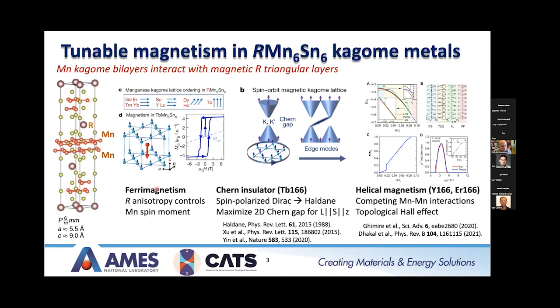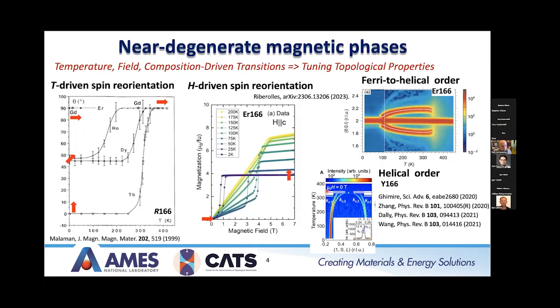So as I said, a lot of these heavy ones, you get ferrimagnetism with the rare earth anisotropy controls. But then also on the other side, if you go to non-magnetic yttrium and even for erbium, as I'll show you, you get competing manganese-manganese interactions, competing interactions between the layers, which can lead to helical magnetism. And then depending on the conditions, you can observe a topological Hall effect. Okay, so that's kind of what drove us into real interest in these materials.